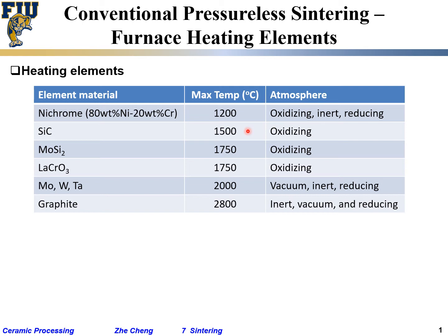The limit is not because it melts, but because silicon carbide starts to go through oxidation in air. For a typical heating element, you expose the element to air, and you are limited to roughly 1500°C. Higher than that, the carbon becomes carbon dioxide and silicon becomes silicon dioxide.